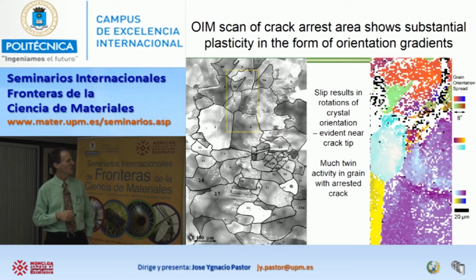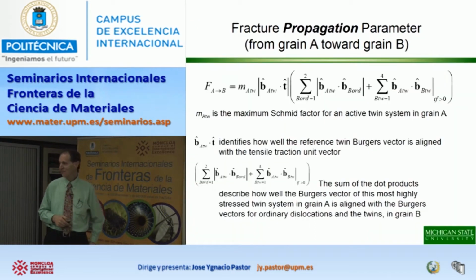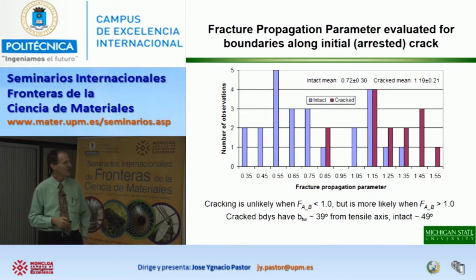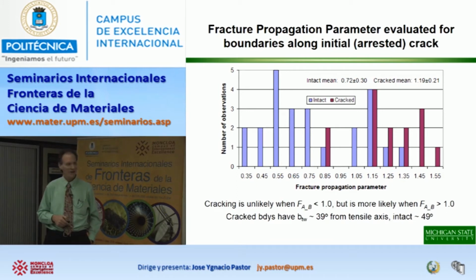So now the question is, if we characterized all of the grains that are downstream of this crack, could we predict which way this crack is going to go? In fact, there's a sense that it's heading this way because it's sort of turning this way. And so we have a variation of that same fracture initiation parameter that I showed you before. But this one pays attention to the fact that I am propagating. I'm going from one grain to another. So there's sort of a one-way directionality that's built into this. I won't go into the details on that. But if I look at the grains above where the crack had already grown and ask myself which boundaries are intact, which ones are cracked, I could get a pretty good separation between those two groups of boundaries using this fracture propagation parameter. So if it's bigger than one, it's more likely there would be a crack. Smaller than one, less likely.